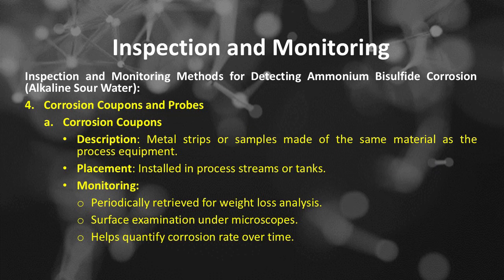Inspection and monitoring methods. Number 4 is corrosion coupons and probes, which includes, number A, corrosion coupons. These are metal strips or samples made of the same material as the process equipment. As for placement, corrosion coupons are installed in process streams or tanks for monitoring, and periodically retrieved for weight loss analysis and surface examination under microscopes. This helps quantify corrosion rate over time.